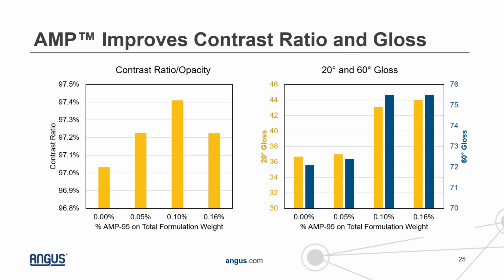We also saw that AMP could improve the contrast ratio and the gloss of these formulations. On the left is a plot of the AMP percentage on total formulation weight by contrast ratio. Our initial control formulation had a contrast ratio of around 97%. But when we were using AMP, in all cases, we saw an improvement to the contrast ratio. The best improvement happened to be with 0.1% AMP on total formulation weight, where our contrast ratio increased to 97.4%. We also saw improvements to gloss.